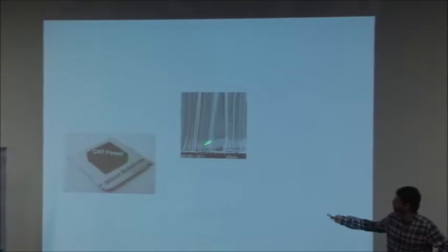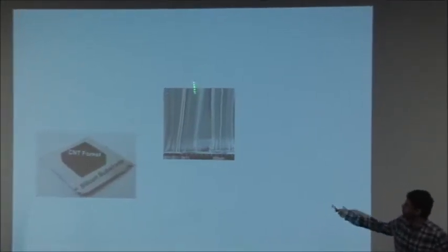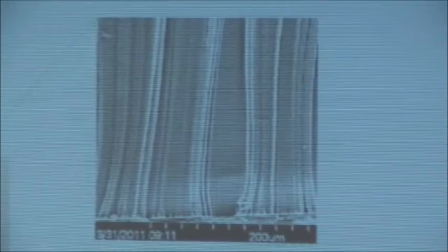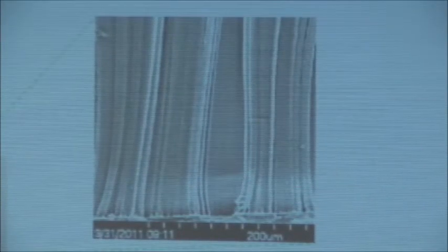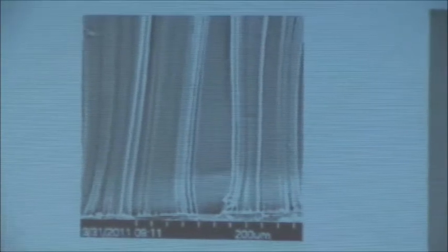And of course, if you look closely in an electron microscope, you will see the individual nanotubes overall pretty aligned. And each nanotube in this case is extending for up to about 2 millimeters. So although the diameter is on the order of a few nanometers or tens of nanometers, the length can be in the millimeter or even centimeter range. And one of them, of course, looks like that if you pull it out and look at it. And so this is the type of structure that I'll be focusing on for the next little while.